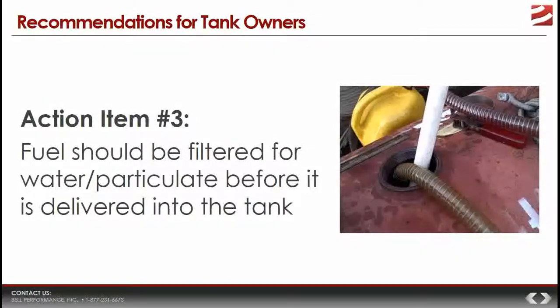If you go a year, you'll have 35 pounds of solids in your storage tank. And then if you're a higher volume one, like a terminal, you've got these really big tanks. Let's say that at a fuel terminal, they go through 60,000 barrels a week, 2.4 million gallons, at 10 milligrams per liter particulate content. That tank, after 1 year, will end up having 11,000 pounds of external particulate solids in it. So a little over time, multiplied over time, can end up being a lot, basically.